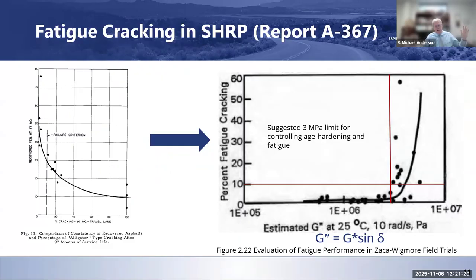Figure 13 on the left is from the Zub and Skog paper, and on the right is from the A367 report from SHRP. So the 1969 paper on the left-hand side is highlighting for us a recovered penetration at 97 months. So that's about 8 years, I guess. So after 8 years in service, this is what they've got with recovered penetration. And they plotted it versus percent cracking in the travel lane. So again, this is in the lane where most of the loading was.